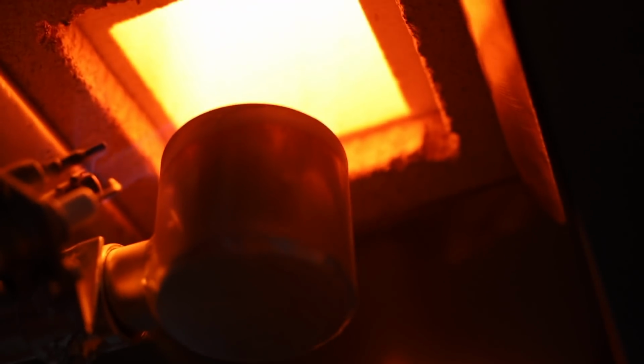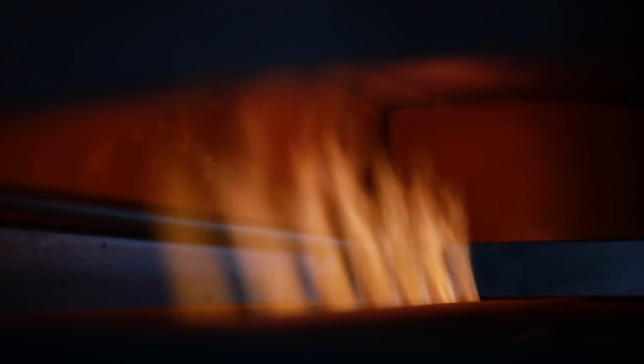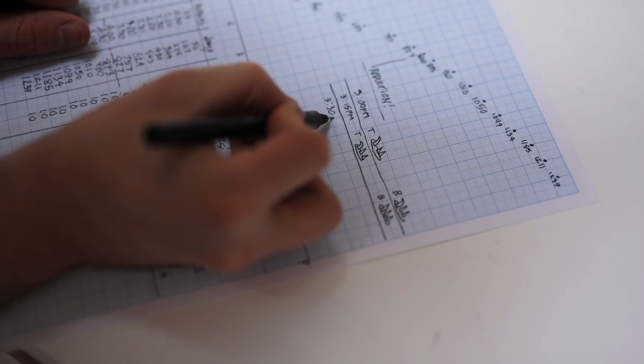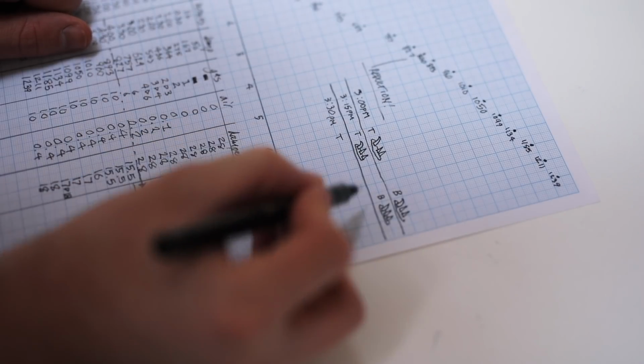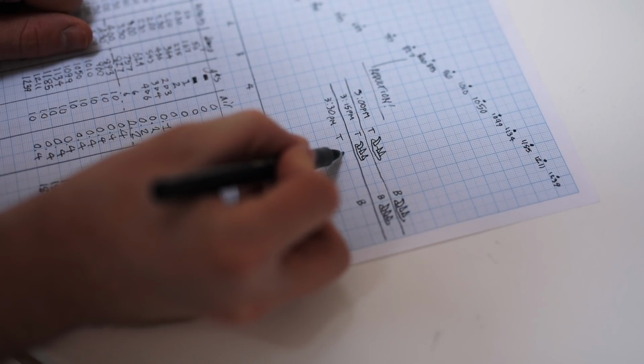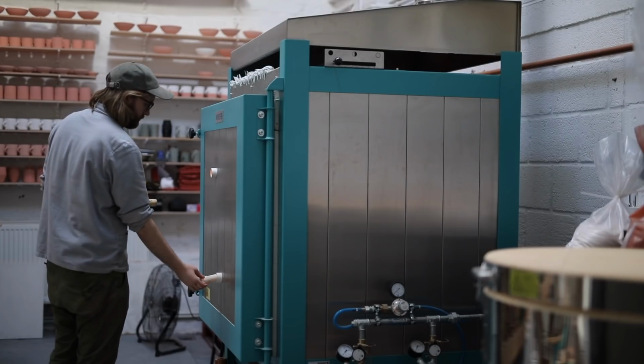As the firing progresses towards the end, which is about 1290 degrees Celsius, the chamber inside begins to become white hot. There are spy holes in the kiln's door I can peek in during the firing, and through these I can observe the pyrometric cones. These melt and slowly bend over at very specific temperatures, and once all the cones are at the right position, touching toes, I can call it a day and switch off the kiln. And for the potters watching, I fire to about cone 10.